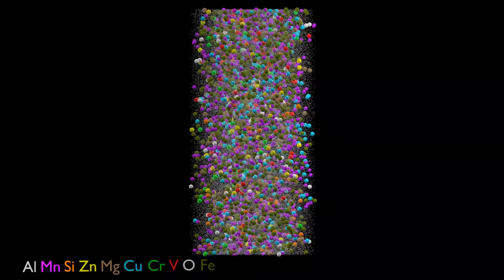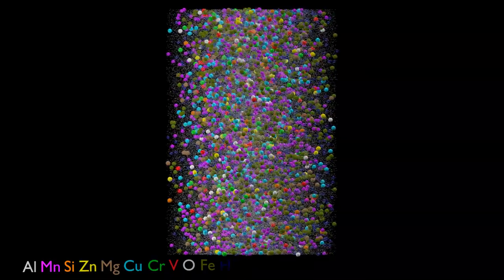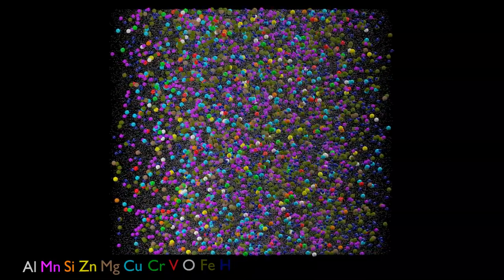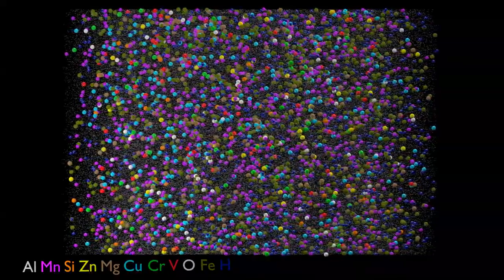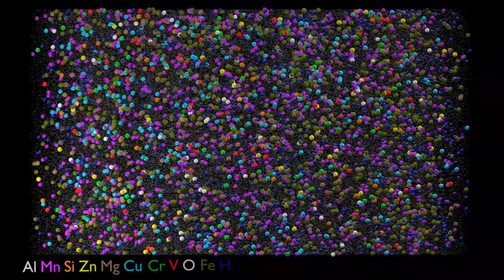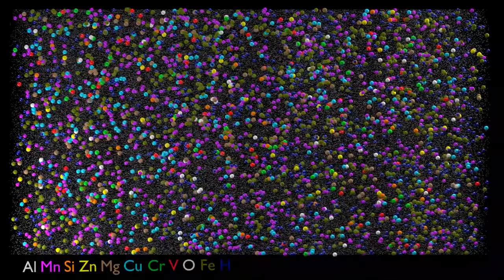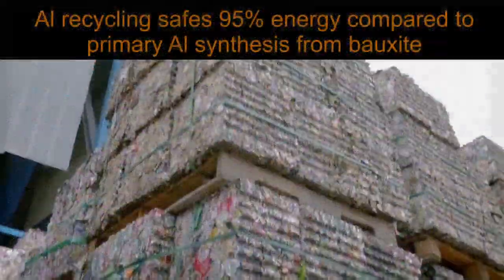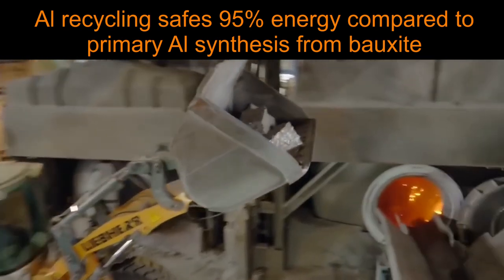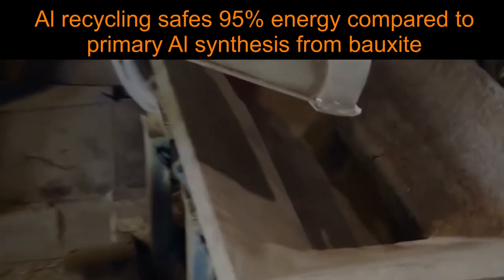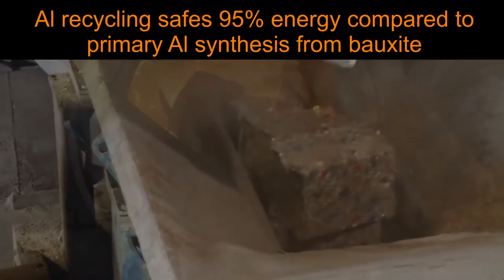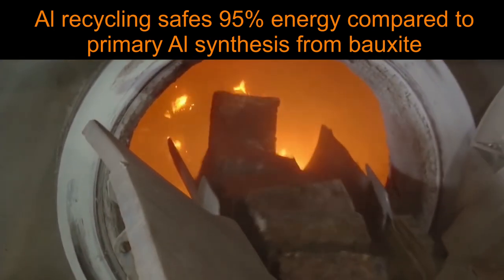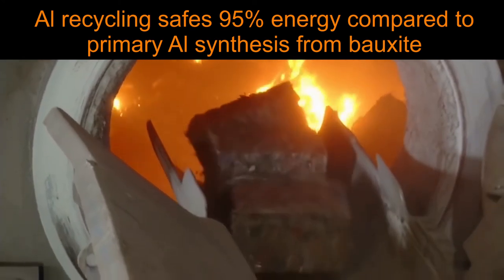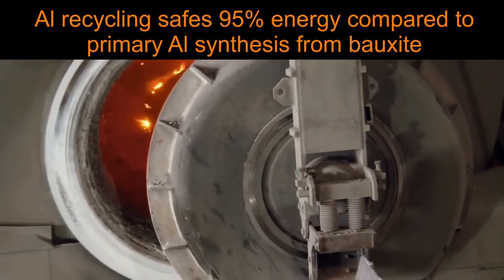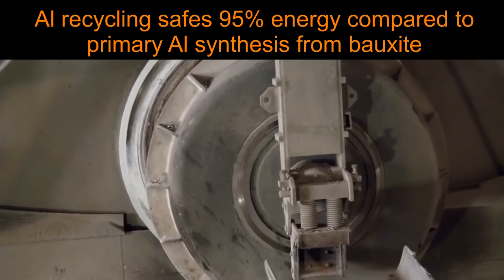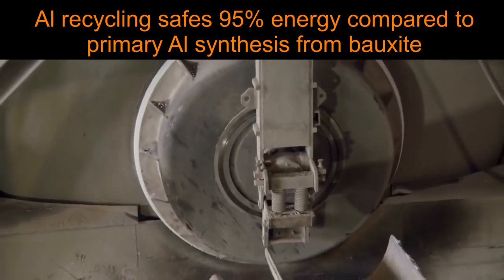The data show that besides the nominal alloying elements, such as about 1% manganese, 1% magnesium and a bit more than 0.1% copper, a number of further elements accumulate over the multiple recycling and re-melting cycles it has been going through. It is therefore an important question in current research to understand how many and how much of these tramp elements can be tolerated in recycled aluminium alloys. A further question is whether alloys can be developed that are upfront designed for high impurity tolerance and hence for high scrap usage.